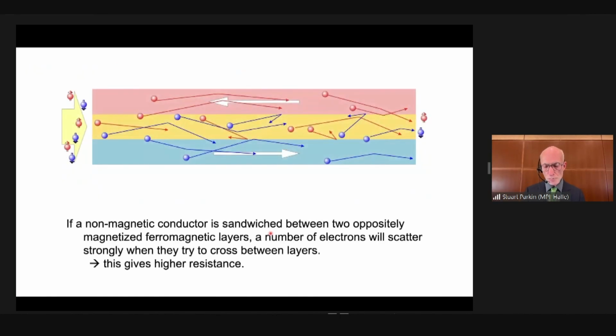Now let's take the example where we build on the atomic scale a multi-layered sandwich, a sandwich consisting of two magnetic layers, shown here as red and blue, separated by a thin non-magnetic layer. This would be copper. Now, when we introduce current from a battery on the left-hand side, in the blue layer on the bottom, just as before, the current will be carried by electrons whose spin is in the blue direction. But in the red layer, the current will be carried by electrons with a spin in the opposite direction because it's magnetized in the opposite direction, as shown by these white arrows.